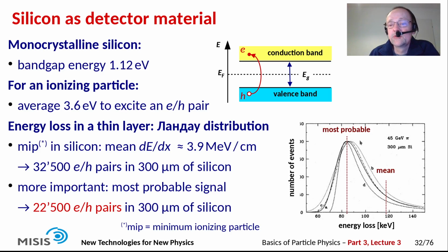But the Landau distribution is actually asymmetric with these tails towards large energy deposits, and what is more important in practical terms than the mean of this distribution is actually its most probable value. And this for a MIP translates into 22,500 electron hole pairs in 300 micrometer of silicon. So now these are small signals, and one of the challenges in designing a silicon tracking detector is to design fast and low noise front-end electronics that are able to detect these small signals with high efficiency.